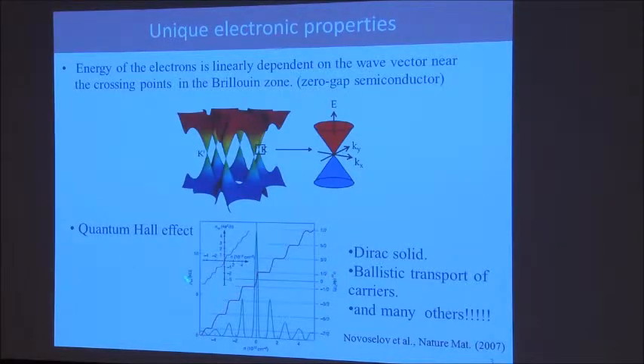The energy of the electrons is linearly dependent on the wave vector near the crossing points of the Brillouin zone, these K points, and this is a zero gap material. There is a disadvantage for applications, since you need a small gap for many applications, but there are ways of inducing a gap in graphene. There are many interesting properties, particularly this electronic structure, that made graphene famous and gave it a very quick Nobel Prize.